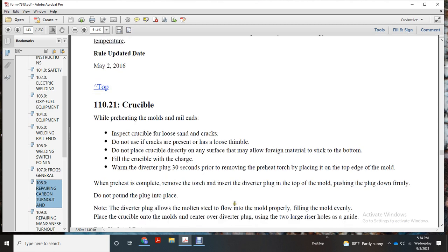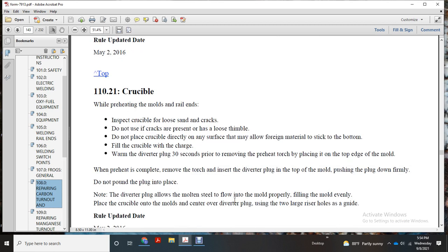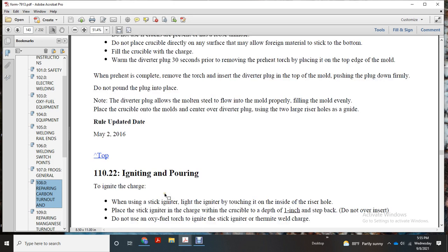Place the plug on the top edge of the mold. When preheat is complete, remove the torch and seat the diverter plug in the top of the mold, pushing the plug down firmly. Do not pound the plug into place. Note: the diverter plug directs molten steel. It allows the molten steel to flow into the mold properly, filling the mold evenly. Place the crucible onto the mold, centered over the diverter plug, using the two large riser holes as guides.